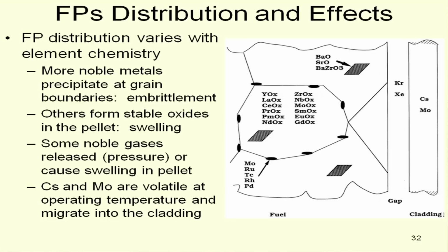Noble metals, and here's some of them, tend to exist as the metal in here, not as an oxide or something else, and they tend to precipitate at grain boundaries, which gives you fuel pellet embrittlement. Others tend to form stable oxides in the pellet, which give you swelling, and that's depicted over here. Cesium and molybdenum tend to be volatile at the operating temperature, and some fraction of those migrate out to the cladding. The noble gases, not nearly all of them, but a significant fraction also migrate out.